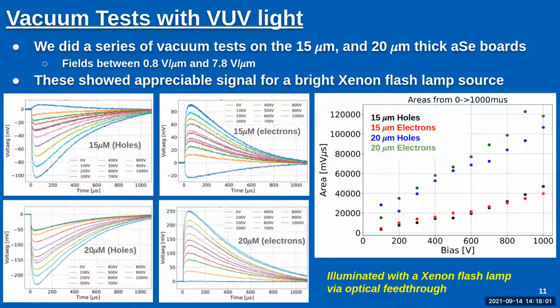We used relatively thick samples to begin with, 15 micrometer thick selenium and 20 micrometer thick selenium boards with fields somewhere between 0.8 volts per micrometer up to about 7.8 volts per micrometer. And these showed appreciable signals when exposed to a bright xenon flash lamp and gave us good confidence that at the very least we see response to VUV light, and that these are signals that we could then take the next step and see if it is viable in a cryogenic environment.